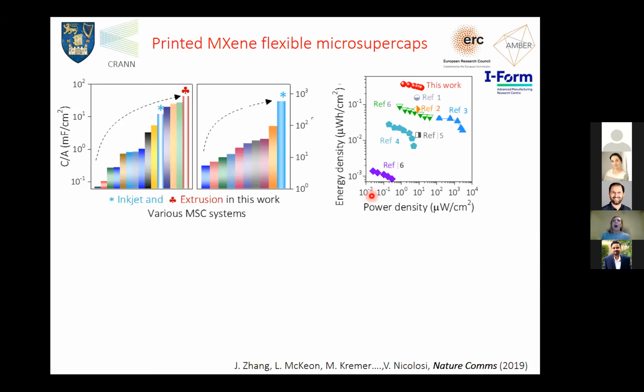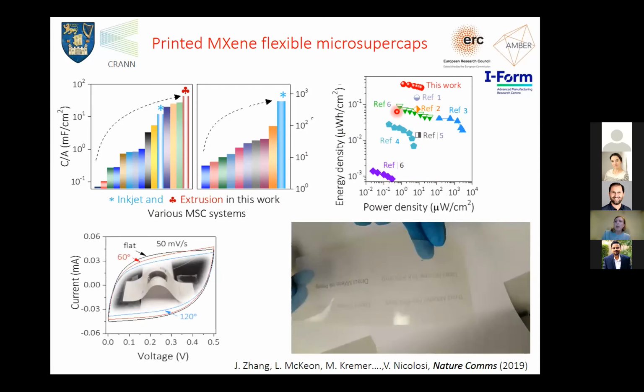So here is a little recap of how they behaved as supercaps. Here I show the areal capacitance, and I compare the areal capacitance we achieved with our devices, the red and the light blue here, to other devices similar in thickness and size that we could find in the literature. And here is the Ragone plot, showing where this work lies compared to other similar devices in the literature. We could achieve very good power density and a truly excellent energy density. Also, we realized that bending of the device didn't compromise the performance. Here are some IV curves of the same device lying flat and then bent 60 degrees, 120 degrees, and so forth. This was recorded at 50 millivolts per second.